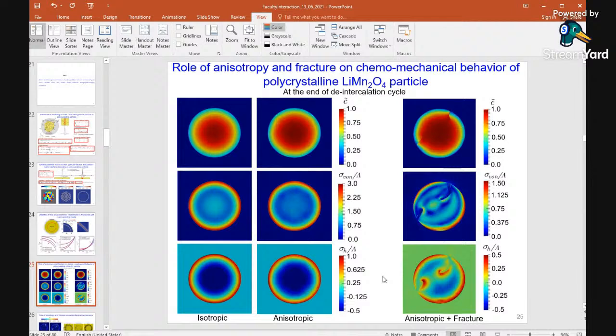first we introduce the grain boundary fracture, because the stress is very high. If we see the stress developed in the particle, and if we allow the fracture to happen, we see a fracture happen. And in the first figure in the third column, you see that there is a discontinuity in the concentration. A very complex stress field is generated, and the hydrostatic stress along with the fracture is very complex. You see the tensile hydrostatic stress is generated ahead of the crack tip. So if there is a tensile stress field ahead of the crack tip, what will happen?